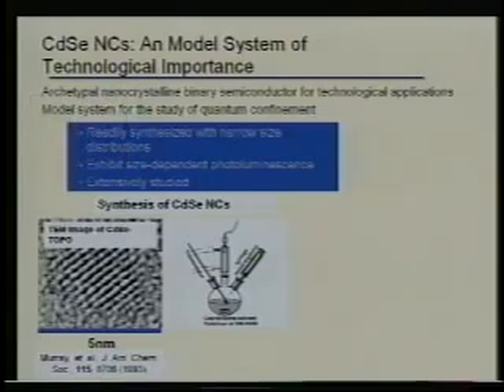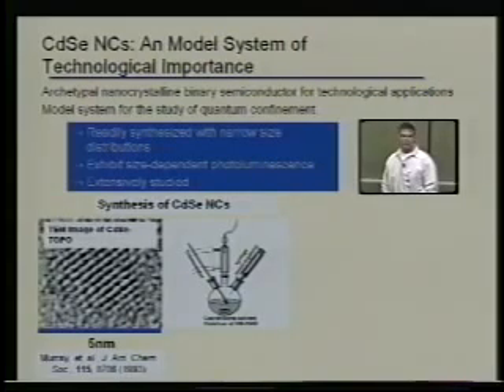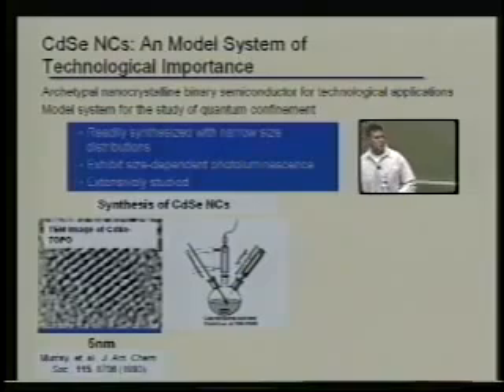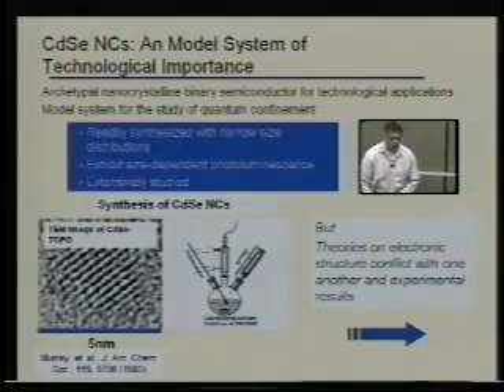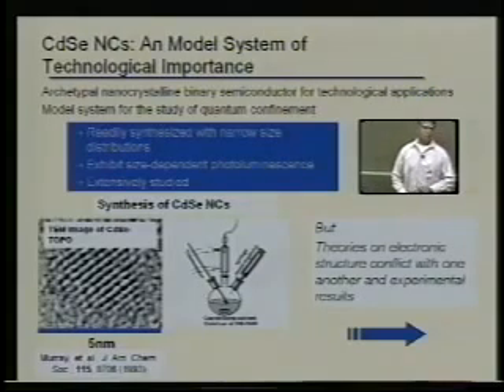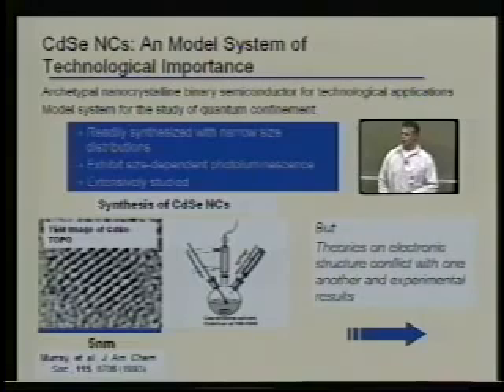So to give you an example that is also relevant is cadmium selenide. The interesting thing about cadmium selenide is that depending on your synthesis protocol, it's usually encapsulated in some sort of organic, or it's in a core shell. So to probe the electronic structure of the inside, you need some sort of technique where you can put a photon in, photon out, such as fluorescence yield NEXAFS, and you can actually probe material that's buried. So in cadmium selenide, there's a number of theories about what should happen with the electronic structure that are in a little bit of conflict.